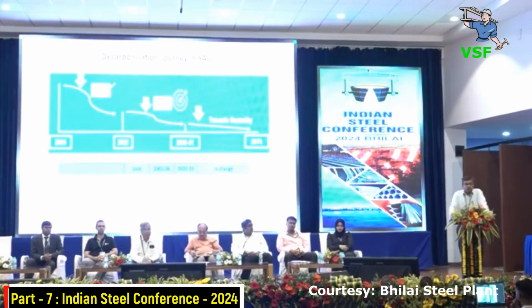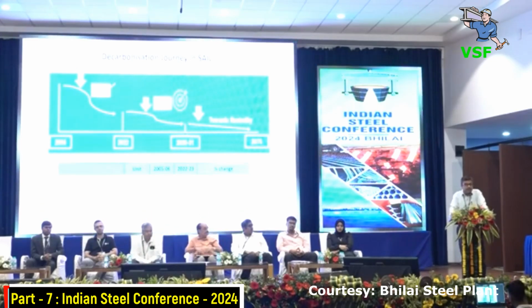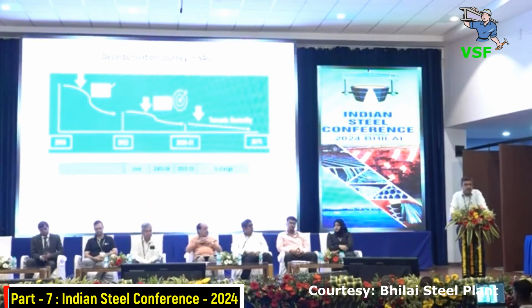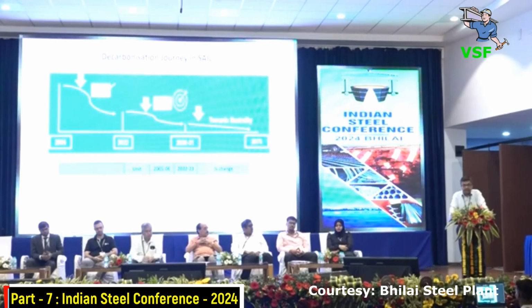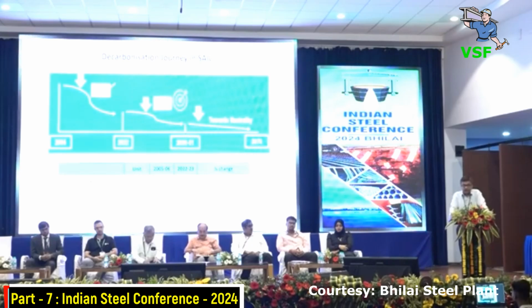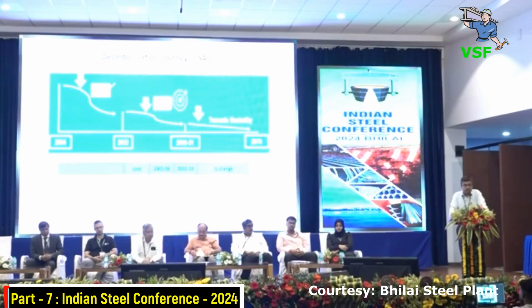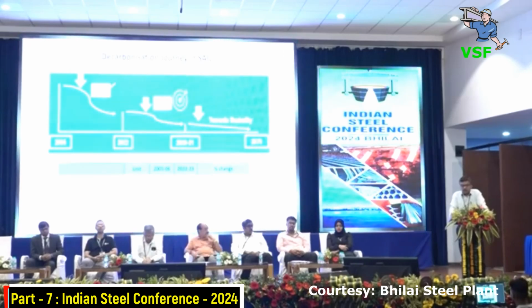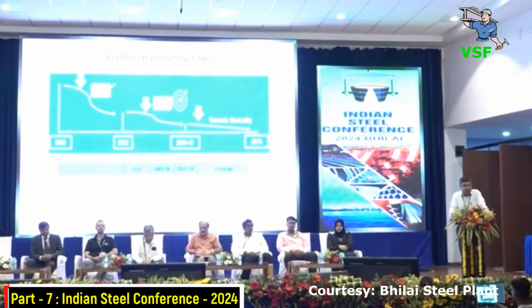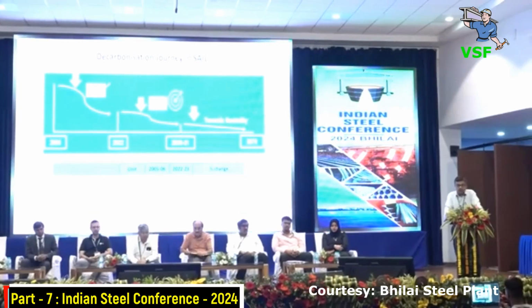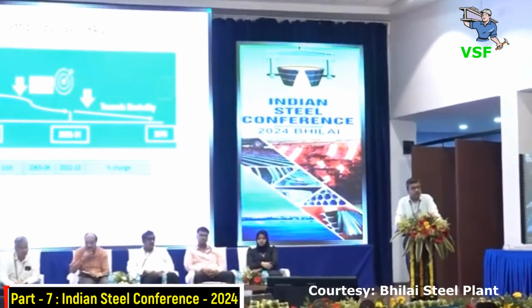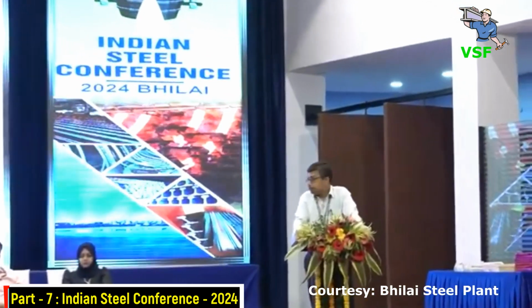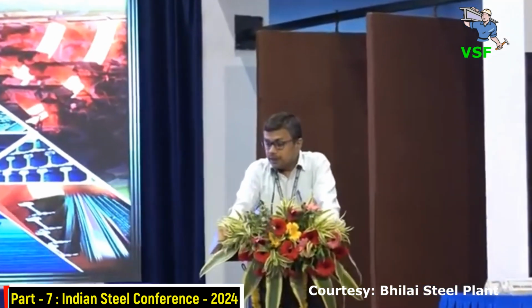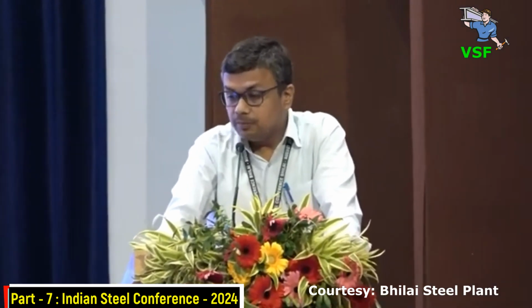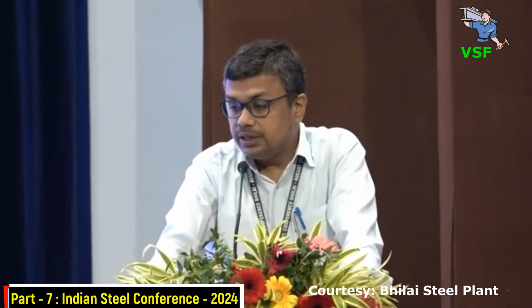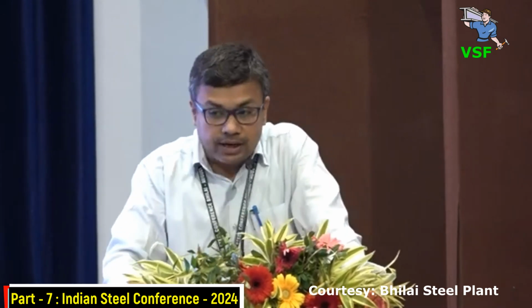And to mitigate that risk, SAIL has come a long way from 2005-06, when SAIL had 3.1 ton of CO2 emission per ton of crude steel. And in 2022-23, it has come down to 2.49. And our target for 2030-31 is 2.19. So we have recorded a 19.7% improvement in the last 20 years, but we have to go for further improvement.